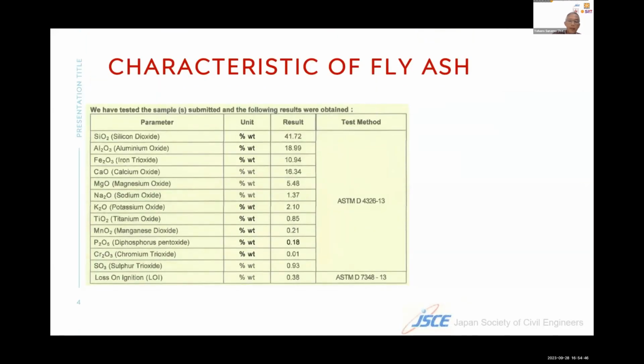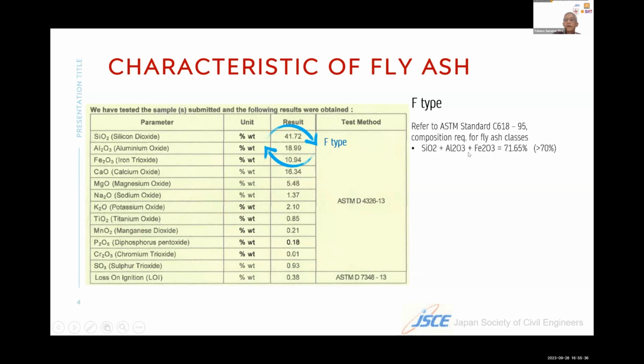And this is the characteristic of the fly ash. Based on the following fly ash sample characterization from test data, there are several important mineral contents in fly ash that indicate the type or class of fly ash. From this test, we can see that this fly ash is Class F, because the total of silicon dioxide, aluminum oxide and iron trioxide is more than 70%. This is the class of fly ash that we use for our factory in Makassar.